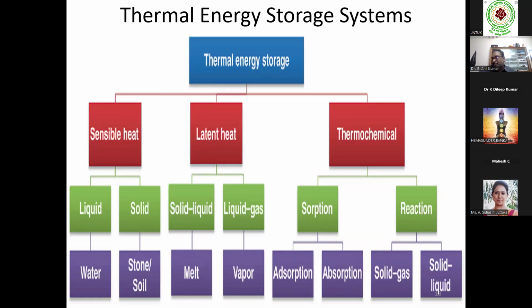Some air conditioning systems use low tariff electricity to freeze water during the night. The ice is then used to cool the air during the day. The latent heat of fusion of ice is, we know, around 330 kilojoules per kg. That is, 1 kg of ice is able to absorb nearly 330 kilojoules of heat. Moreover, the ice remains at a temperature of 0 degrees centigrade while it is melting, and this simplifies the delivery of the stored energy.